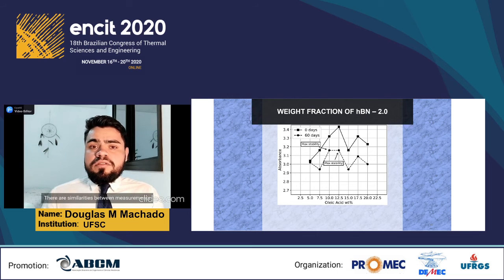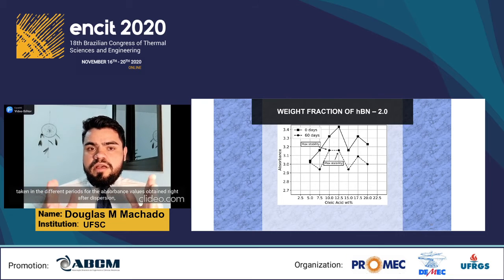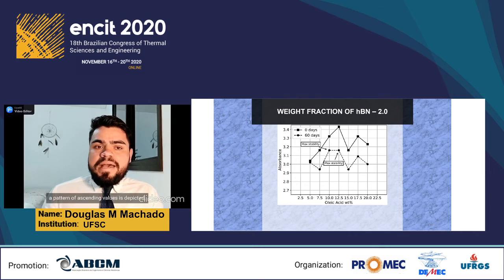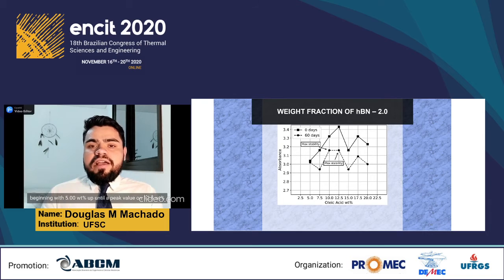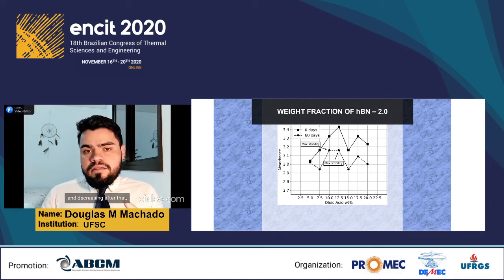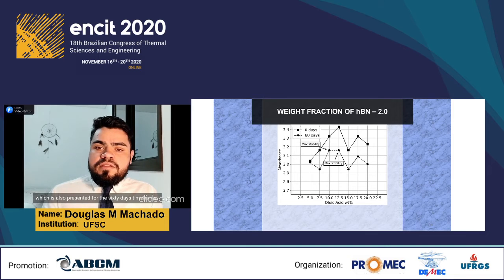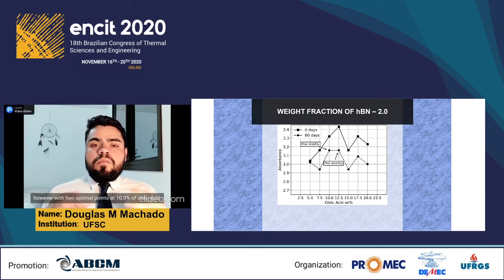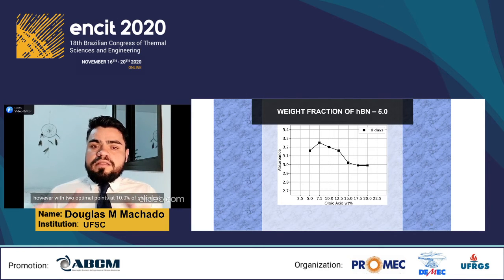There are similarities between measurements taken in the different periods. For the absorbance value obtained right after dispersion, a pattern of ascending value is depicted, beginning with 5% up until a peak value at 12.5% and decreasing after that. The same is also presented for the 60 days time frame, however, with 2 optimal points at 10% of oleic acid.